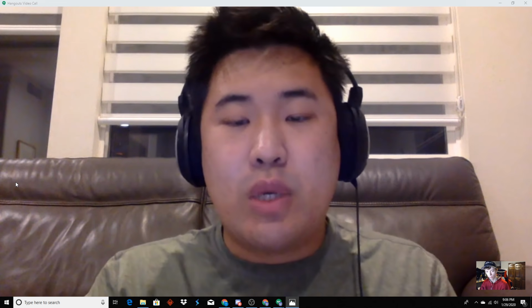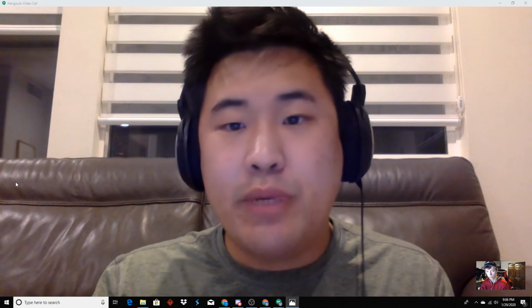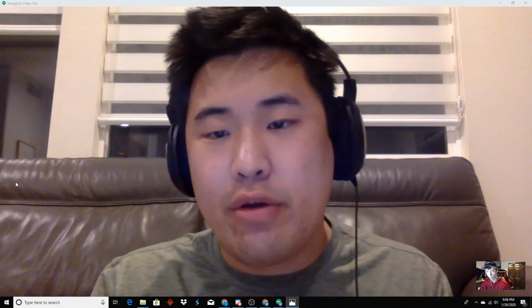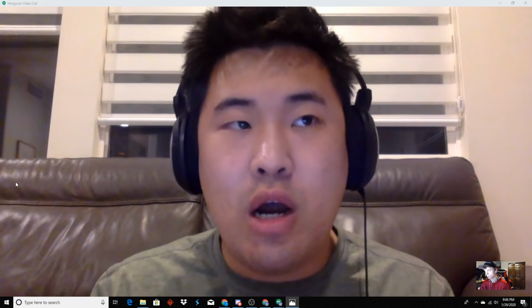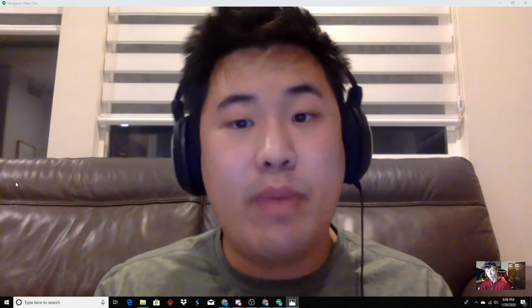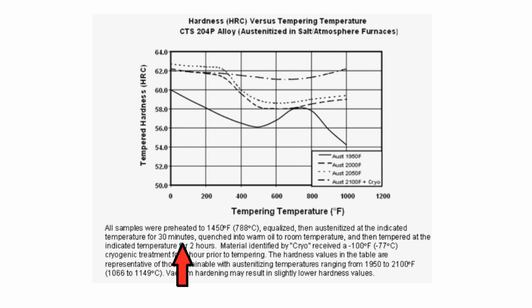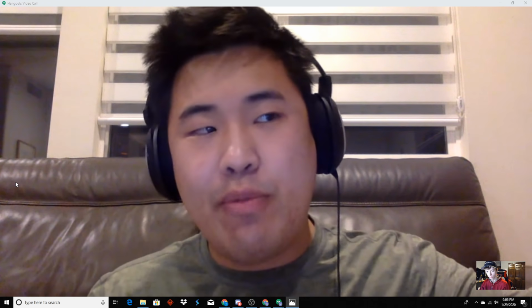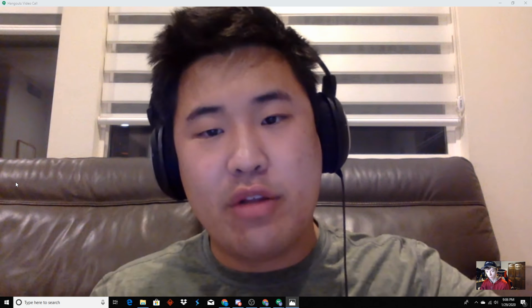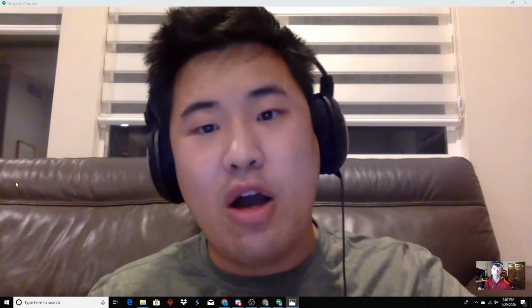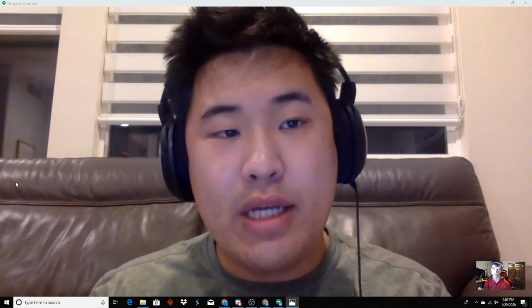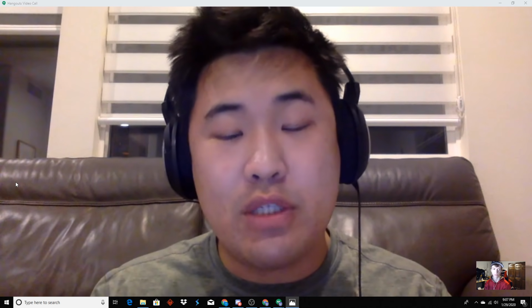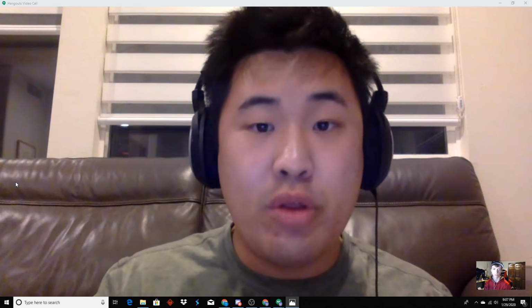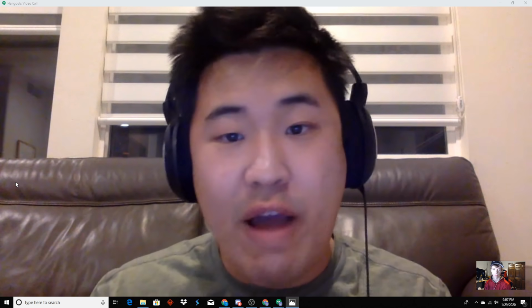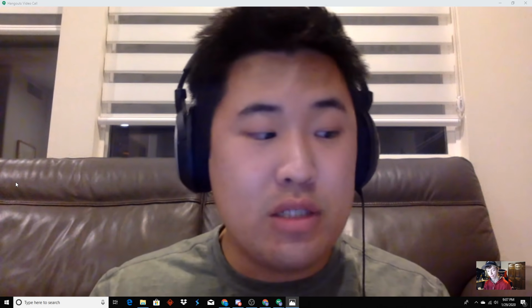But my thought process was, well, they can't all be right, but probably some of them are right about some things and some are wrong about others. One of the things that I thought was weird was Carpenter suggests a soak time of 30 minutes, which is very long. If you think about the temperature you take M390 or 204P to, it's a very high temperature. To soak for 30 minutes is a very, very long time. I'm thinking that's just too long, right, in my head when I read that. Whereas Bohler for M390 was suggesting, at a temperature even a little below what I heat treated this to, only 5 to 10 minutes. Wow. So that was a substantial difference.